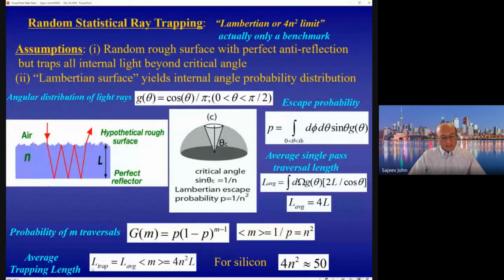So this gives a trapping length, which you could estimate as being the average length of a single bounce times the average number of bounces, which is 4n squared times the actual thickness of the solar cell. And for silicon, with a refractive index of about 3.5, this corresponds to an increase in the path length by about a factor of 50. So far, no real solar cell has even achieved this Lambertian limit.